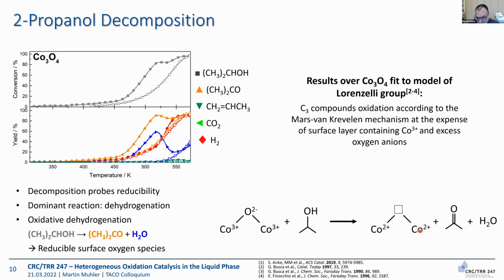You know that mechanism from literature very well. That's the so-called Mars-van Krevelen mechanism that is also typical for high temperature gas phase catalysis. And what has happened now in addition, now you need oxygen from the gas phase to re-oxidize the active site so that we end up here again and can start the catalytic cycle again.